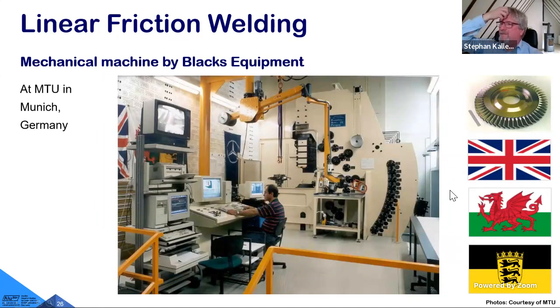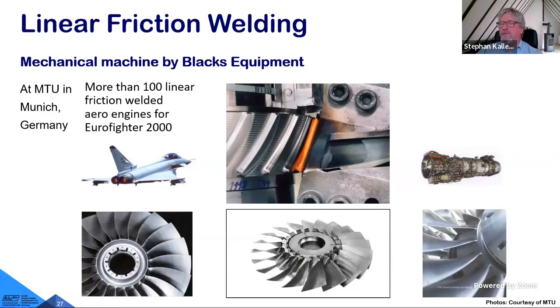So here you see, for example, the machine at MTU that has been built by Blacks Equipment. And you see the flags in the background. There's a Stuttgart flag. Oh, this is not for MPA, I have to say. This is for Rudolf Reinhardt of Mercedes-Benz, who provided knowledge on rotary friction welding and fixturing. And the tooling that you see here, not everybody can access that room. This is really impressive stuff. And then we see the Welsh Dragon for Davis Nicholas, and the Union Jack for Roger Black. This was a very nice collaboration in the, I would say, late 70s, early 80s, where linear friction welding was transferred from the United Kingdom to Germany. And MTU was in a delightful position to produce the fan blades of the Eurofighter aircraft. You see again these little blocks which are necessary for clamping the parts.